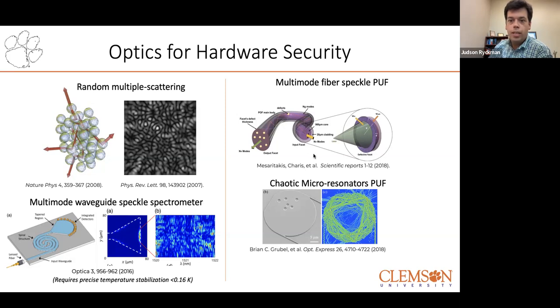Also, we see more recently intentionally designed physical unclonable functions based on multimode fiber, the speckle patterns you get out of those, and now more integrated work out of Amy Foster's group at Johns Hopkins, compact chaotic resonators. Now, many of these platforms suffer from a really strong sensitivity, not only to the structure of the device, but also to the environment. So you see this example here. Despite being unclonable, it will also decorrelate with itself if the temperature is shifted by 0.16 degrees Kelvin. So this is also a problem that needs to be addressed.